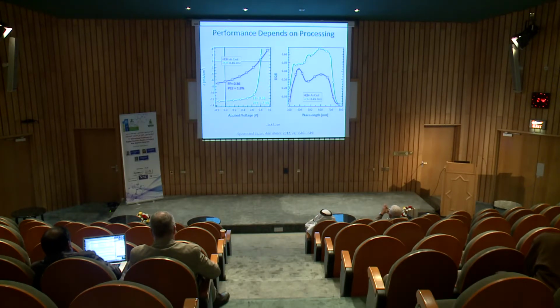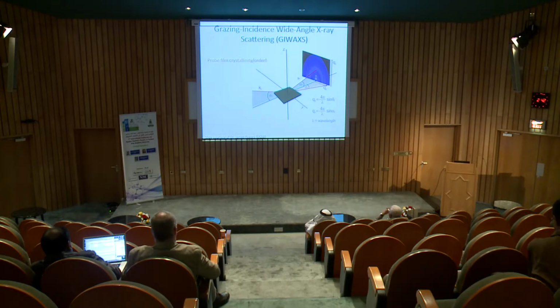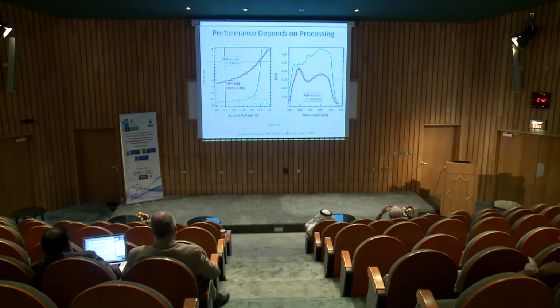And from here, you can see that for the devices processed differently, the real difference is the amount of photocurrent generated by the T1 material. So next, when we see the difference in the device efficiency, we hypothesize that when we make the film differently, what really changed is the film morphology. So when we change the film morphology, we change the device performance. Now the question is, how are we going to probe the film morphology difference between the two devices?